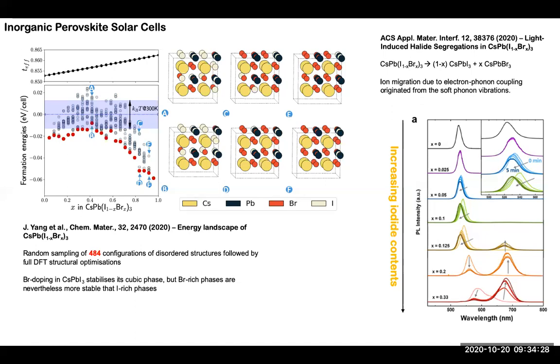So if you think about photovoltaic application, that scattering is perhaps going to lose you photovoltaic efficiency, so it might not be desirable. Of course, if you go down to lower temperature, your peak will be much sharper, because the phonon got quenched.